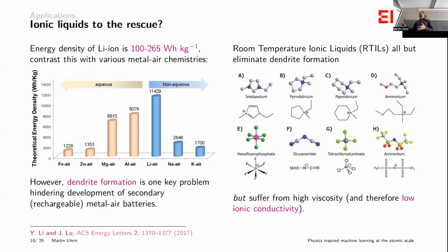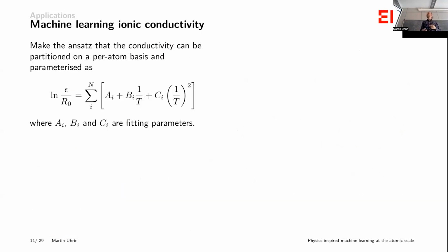The problem with almost all of them is that they're very viscous. If you make this thing, it's almost like honey. So you can imagine that's not ideal for an electrolyte where you want to have good conductivity of your ions through it. So the goal, in a way, is just to find a combination of these that have, let's say, lower viscosity and therefore higher ionic conductivity.